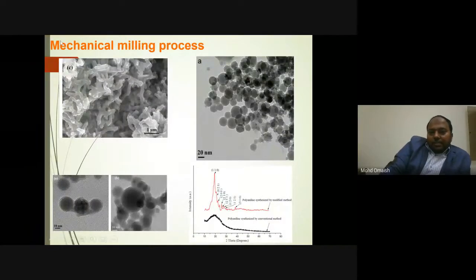Another approach to change the morphology is mechanical milling. In this case, we used mechanical milling in our lab on polyaniline fibers, and by simple long-time milling, we were able to break these fibers into small spheres. This is the original first stage, this is the intermediate, and this is the last stage, in the TEM images.